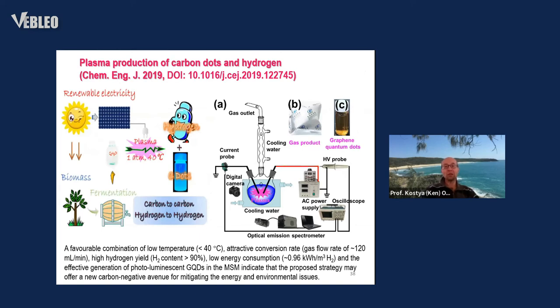One example of plasma discharges inside the liquid is when they insert two electrodes and generate an electric spark in an ethanol solution, where we can have a carbon precursor. This electric spark leads to a very interesting process that simultaneously produces gaseous hydrogen, which is collected and used as a gas product, and solid objects called carbon quantum dots, in particular with graphene-like structures, so we also call them graphene quantum dots.